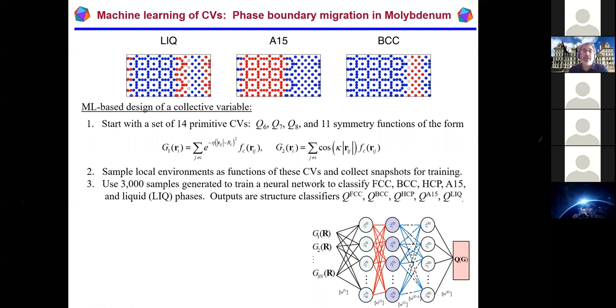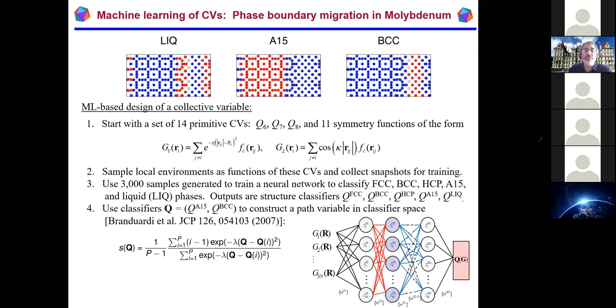Now, we're not going to use the classifier vector per se as a collective variable. What we're going to do is build what's called a path collective variable to move between one phase and another, all right? So if you have P phases of interest, and in these examples P is equal to 2, because I have 2 phases I want to study, even though I have 5 possible phases, I just want to explore the transition between these two. So I construct a path collective variable in classifier space, right? Q is my instantaneous classifier that I get for any arbitrary configuration. Qi is the ideal classifier, and S is a variable that has a particular integral value in one of the two phases. And you can guide the sampling by using an orthogonal variable, Z, that looks like this.